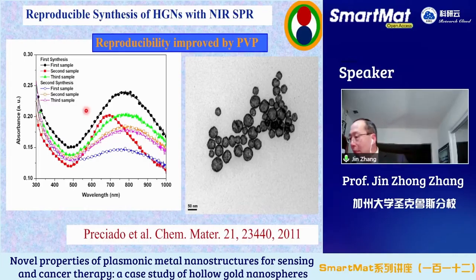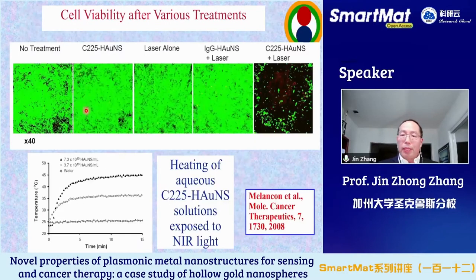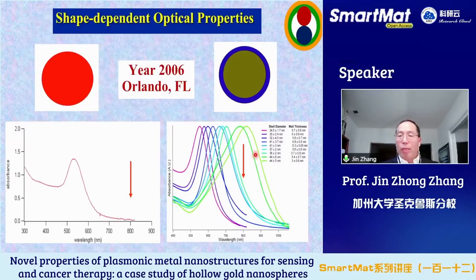However, that's an interesting twist. I'm going to try to wrap up in about 3 minutes. The twist is as follows. The sample we want the most is 800, as I told you, because we can make any of these samples, but we want the one around 800. That's what the biomedical purpose is best satisfied. However, the catch-22 here is that this sample is the hardest one to make. Why? Because it has the thinnest shell.